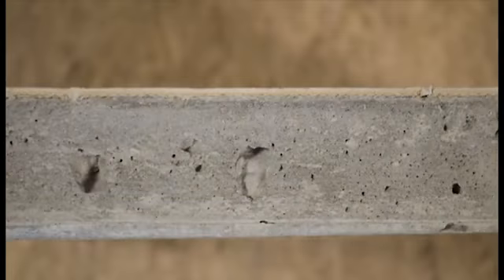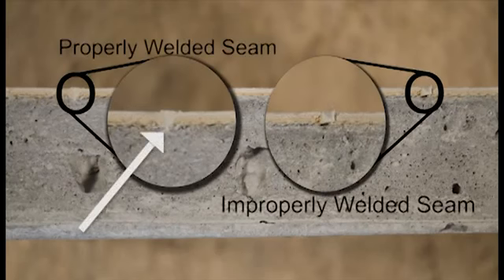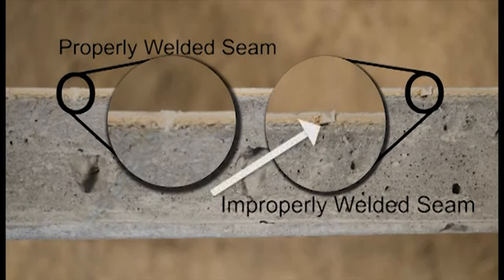Here in this cross section, you'll see on the left side of the picture a properly welded seam. You'll notice the weld rod is welded in the entire groove, where on the right side, on the improperly prepared seam, you can see a gap underneath the weld rod. This gap can result in a failed seam. The picture you see here is a failed welded seam due to improperly cutting and grooving the seam.